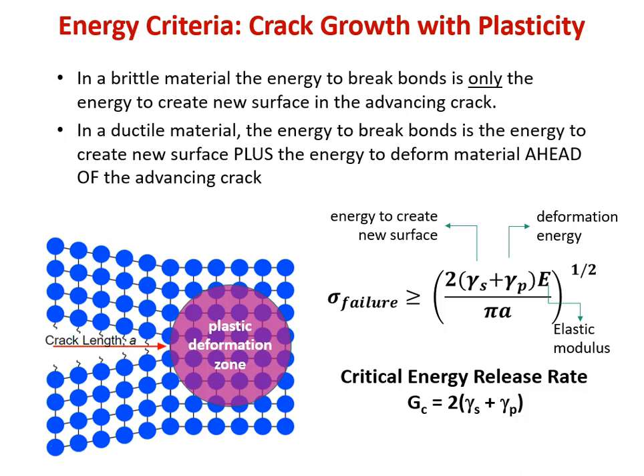If that were the case, most materials would not survive in service. And that's, in fact, equating fracture energy to merely the energy to create a new surface. That's only the case for very, very brittle materials, like some very brittle ceramics. In reality, we have a lot more ways to absorb energy in materials, thank goodness, other than just creating surfaces, because it's not a lot of energy to create a surface.